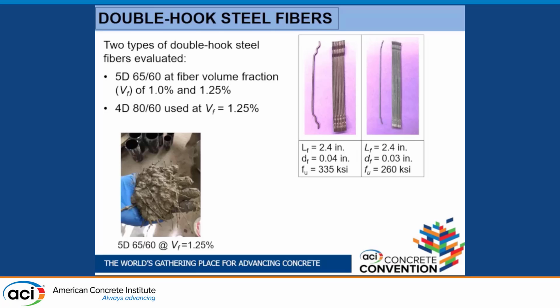You can see now you have 2 hooks here, and a 1.5 hook on the other one. The left one is called a 5D 6560 fiber. The one on the right is a 4D 8060 fiber, both manufactured by Bekaert. We evaluated the 5D, the one on the left, at either 1 or 1.25% by volume, and the one on the right at 1.25% by volume. Both fibers have the same length, 2.4 inches. Nominal tensile strength for the left is 335 KSI versus 260 KSI for the one on the right, and the diameter for the one on the right is a little smaller, so the aspect ratio is larger for the 4D versus the 5D fibers.